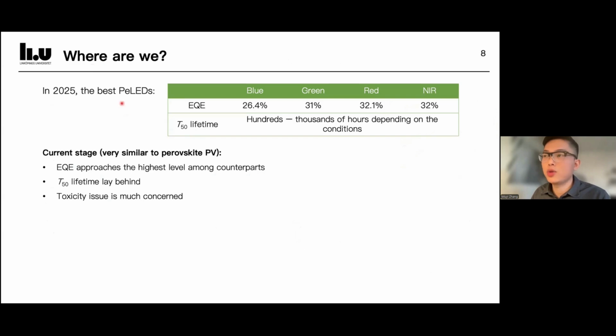So, where are we now with PeLED in 2025? If you look at this table, the best reported EQEs have reached 26% for blue and 31% for green, and over 32% for red and near-infrared. These numbers are already on par with OLEDs in many cases, and that's something we could hardly imagine a few years ago. But of course, there's still a big gap in the T50 lifetime. Right now, it ranges from hundreds to maybe a few thousand hours, depending on the device and the conditions.